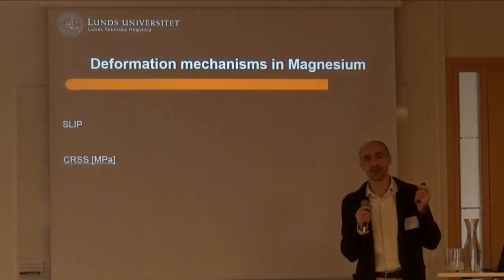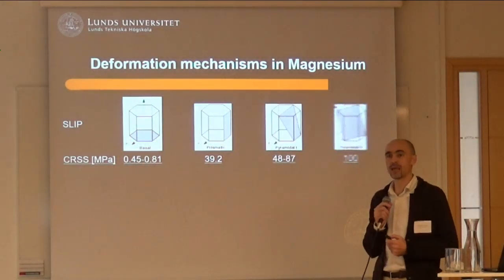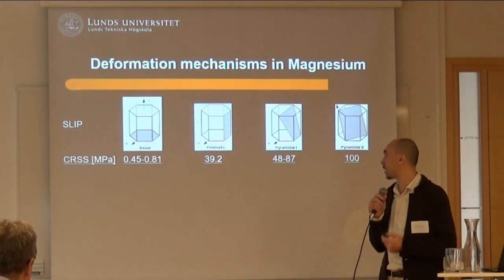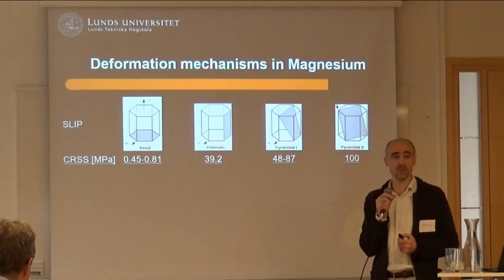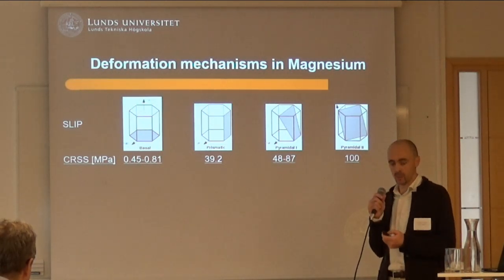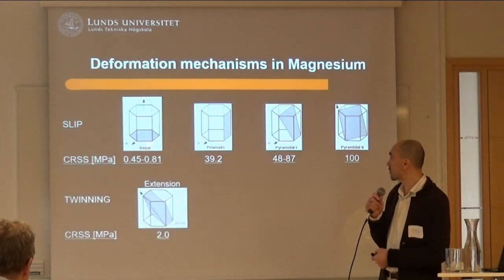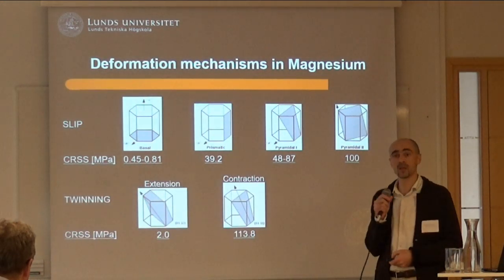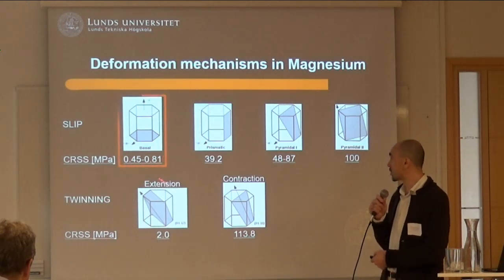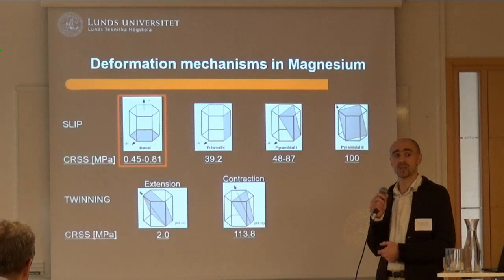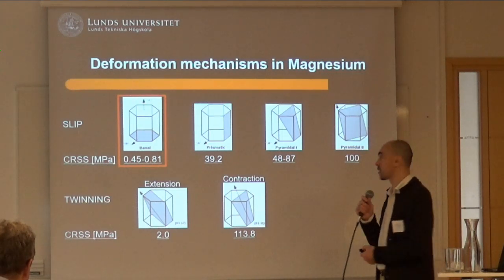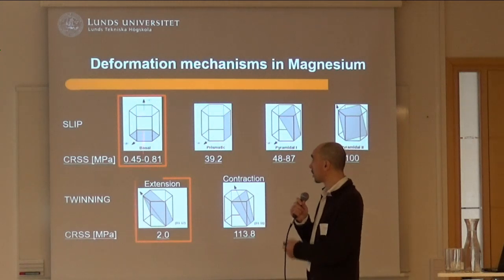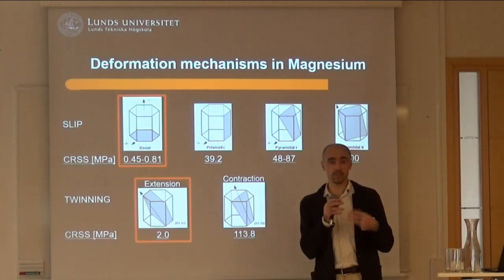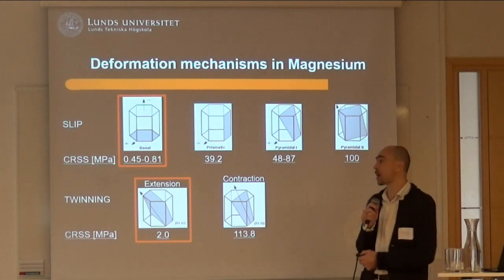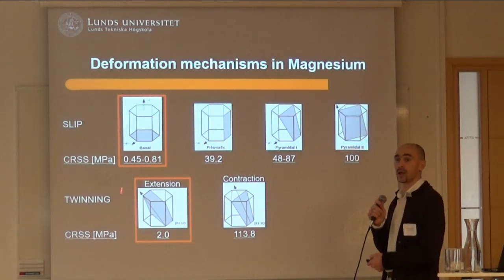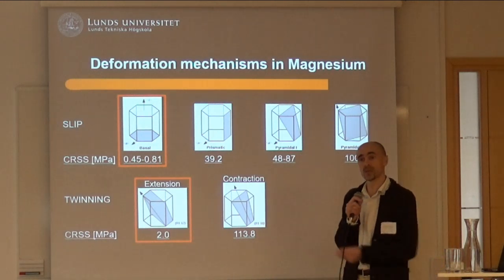Sorry, one indicational slide about magnesium. Unlike copper or steel or aluminum, magnesium has a so-called hexagonal close-packed lattice, and the strength of magnesium is controlled by plastic deformation on the basal plane and so-called twinning. If you look at the critical resolved stress necessary to initiate plastic deformation in your material, these two systems work in parallel and they're quite soft. So basically the structural efficiency improvement can come by restricting plastic deformation in these directions.